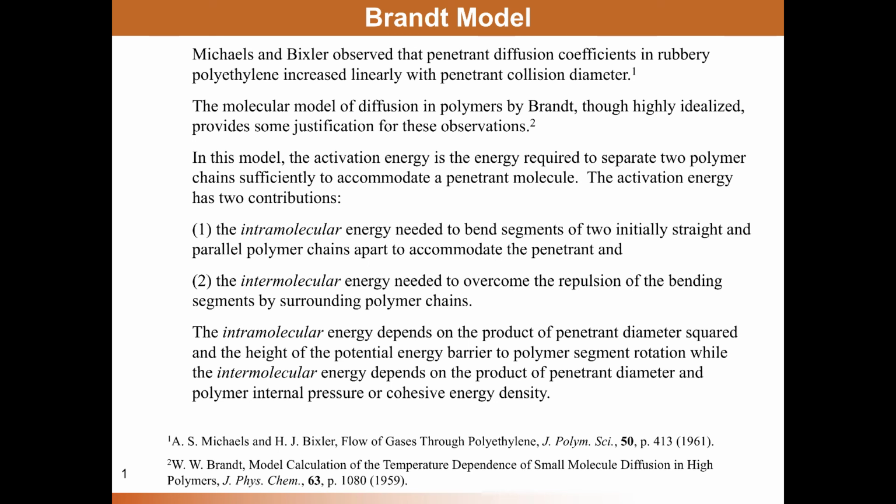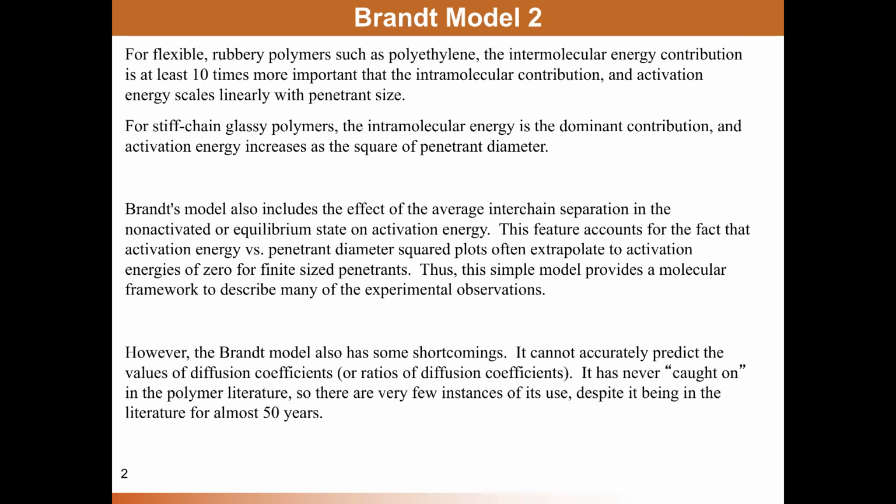In fact, we're often changing penetrant size over a narrow enough range that we often, empirically at least, can't distinguish between activation energy that depends on the square of the diameter and one that goes linearly with diameter. And so we don't emphasize this model, certainly not in the modern literature very much. And I only bring it up here to remind us that there are likely other contributions to the activation energy of diffusion than simply the polymer cohesive energy density.